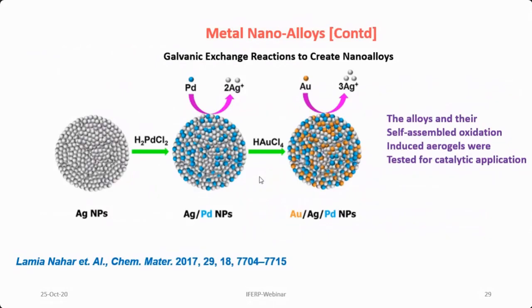There is another approach for creating metal nano alloys, that is called galvanic exchange. We know that galvanization happens with electrochemical processes. With their native redox properties, and the difference of redox potential, galvanic exchange reactions take place between metals. What they did is they created a cluster of silver nanoparticles, a stable cluster, not one that is aggregating and ripening into larger particles, but stable nano clusters of silver nanoparticles. In that, they put a precursor of palladium.